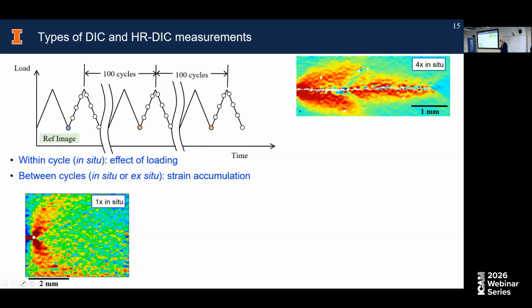So between cycles means, let's say that you go to the same point, the bottom point of the fatigue cycle each time, and you correlate with some initial image, and you can do this with whatever frequency you want. I say 100 cycles here, but whatever you want. So essentially, if there were no change between these points, meaning that there was no damage accumulation over time, these would just provide no correlation. But they don't. They actually provide some type of result, as is shown up here.